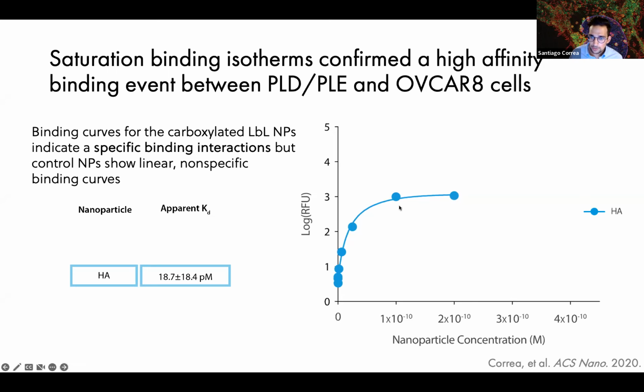And so here I'm showing the results for our hyaluronic acid coated nanoparticles, which have that specific binding interaction, right? And what we see is the classic curve that is normally associated with a specific interaction. And when we fit this data to our model, we find that our hyaluronic acid nanoparticles have an apparent KD for ovarian cancer cells in the upper range of 20 picomolar.